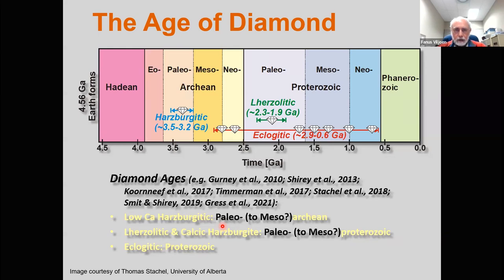a team at the Free University of Amsterdam looked at the age of highly depleted harzburgite occurring as inclusions in diamonds, which proved to be 2.95 billion years old, and looked at more calcic harzburgite occurring as inclusions in diamonds, also from Venetia, but the more calcic harzburgite produced an age of 1 billion years. And so at the moment, the thinking is that lherzolitic diamonds and the more calcic harzburgitic diamonds are essentially a Proterozoic diamond source, which probably forms in the Proterozoic through presumably plume processes, which normally result in large igneous provinces, but in the case of the lithosphere, also shows a link between large igneous provinces and the crystallization of lherzolitic diamonds, as well as more calcic harzburgitic diamonds.